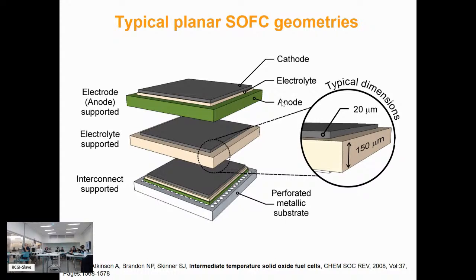From these materials, there are three approaches. One is to use one of the electrodes, in this case the anode, as the support. The green here means it's a mixture of nickel oxide and ceramic, which reduces in the fuel to nickel and ceramic, with a thin electrolyte on the top and then an air electrode.